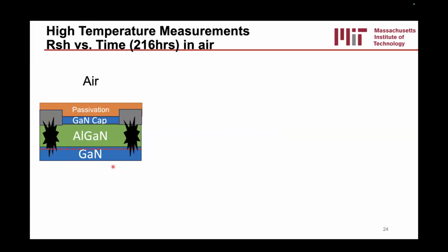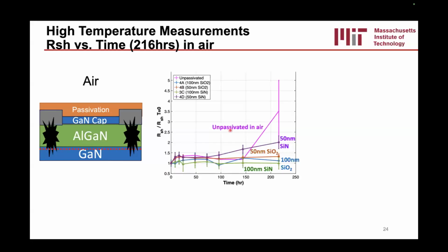Surprisingly, we can also do the same experiments in air instead of the nitrogen environment, as was in the previous slides. And we can also try passivating the sample with a few dielectric layers. So we did that. Surprisingly, unpassivated samples in air can actually last up to, in this case, 150 hours with very little degradation, maybe 50%, not the 5x we saw in the nitrogen environment. Similarly, if we cap the samples with 50 nanometers of silicon nitride or silicon dioxide, or 100 nanometers of silicon nitride or silicon dioxide, those samples can survive up to 216 hours or roughly 9 days.